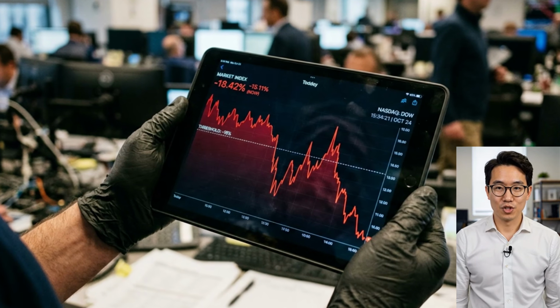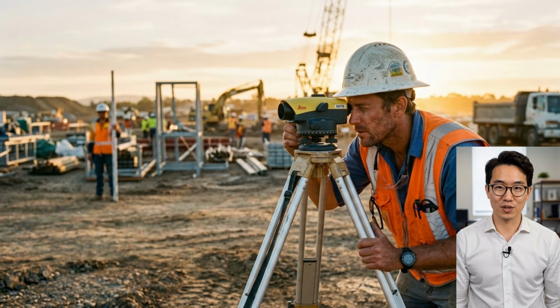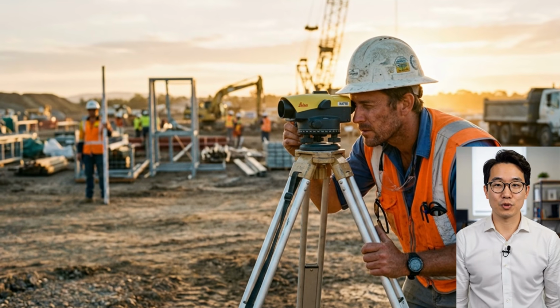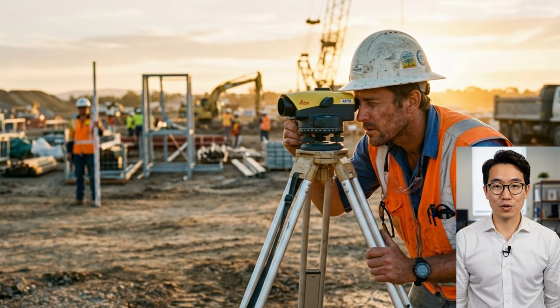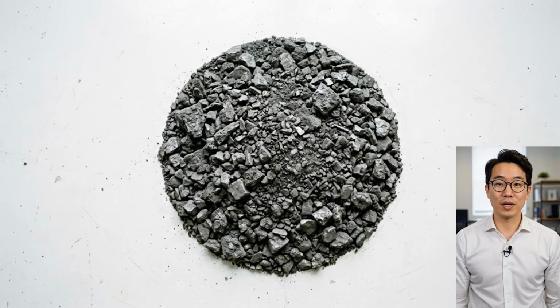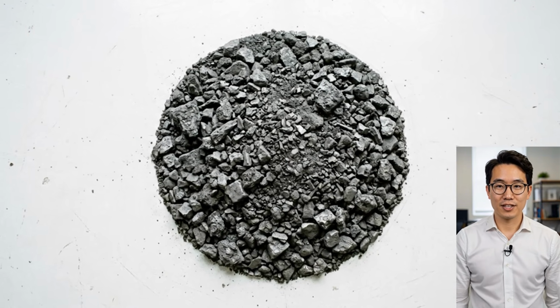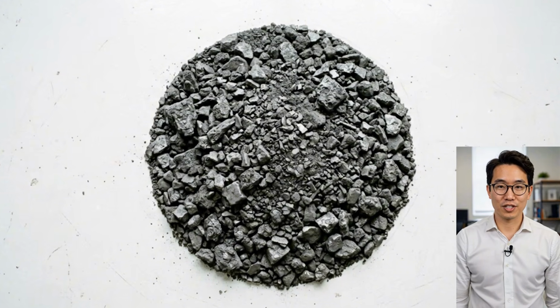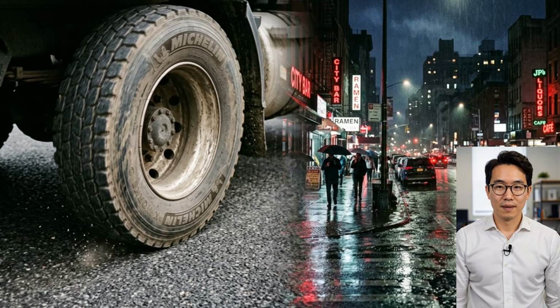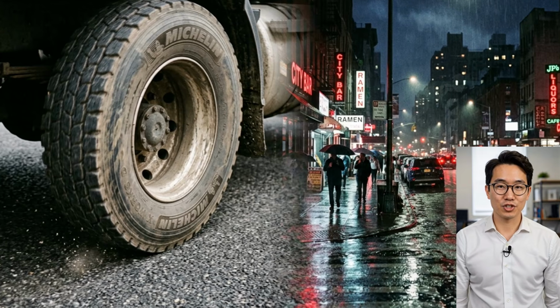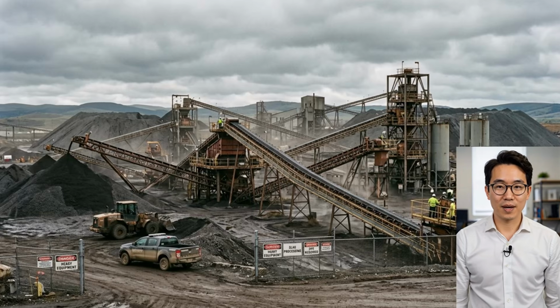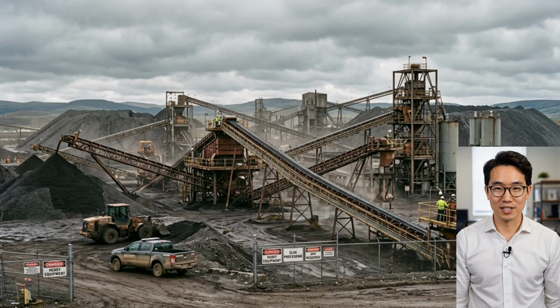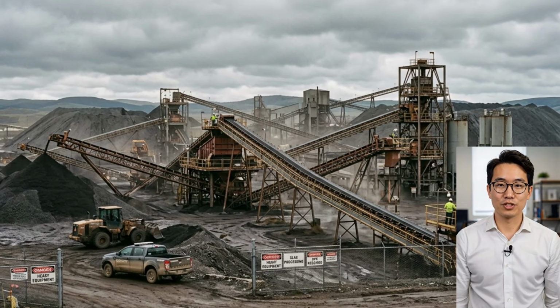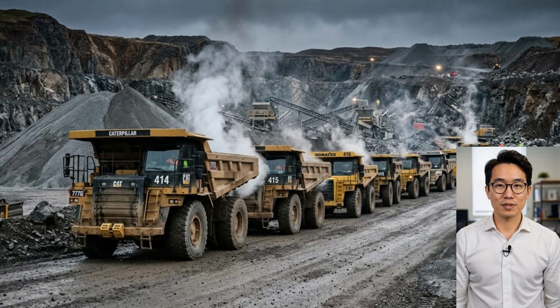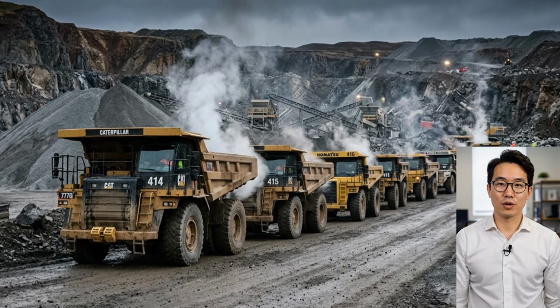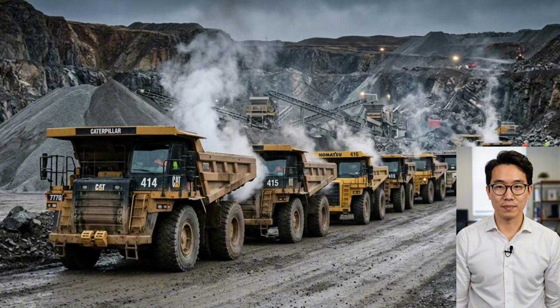The 2022 Chang'an University study makes that trade clear. It found strong gains in high-temperature stability, but it also showed weaker low-temperature performance as steel slag replacement climbed too high. In that study, replacement levels above 80% did not meet the standard requirement. That is a big warning sign. It tells engineers there is a useful window, not a free pass. Around 60% replacement in one part of the mix kept showing up as a sweet spot, but a sweet spot is not the same as a universal answer. Climate, traffic, and local materials still matter.